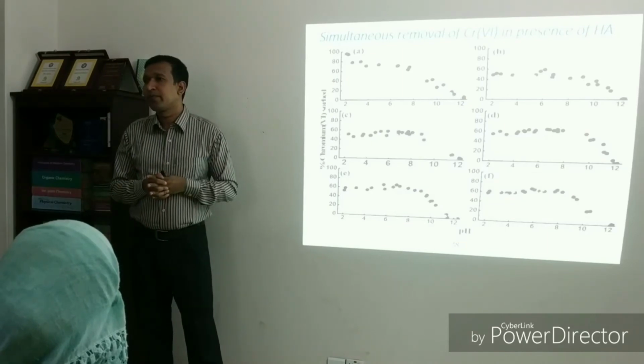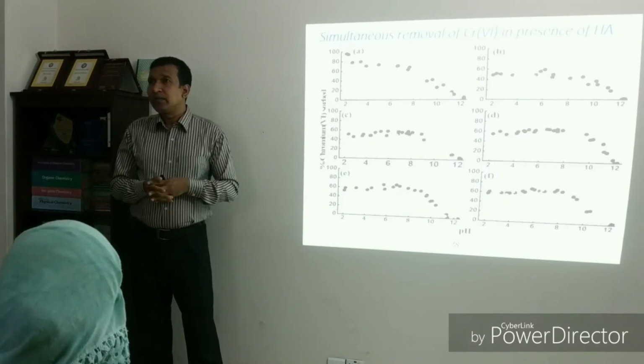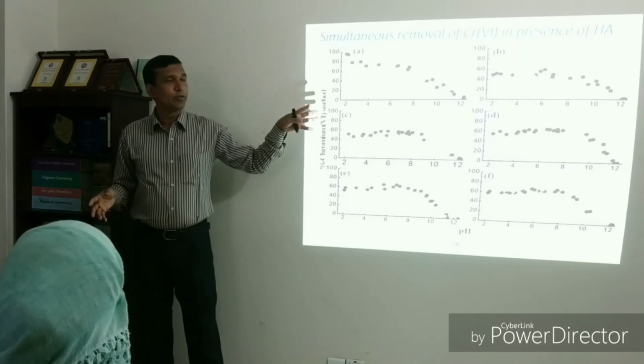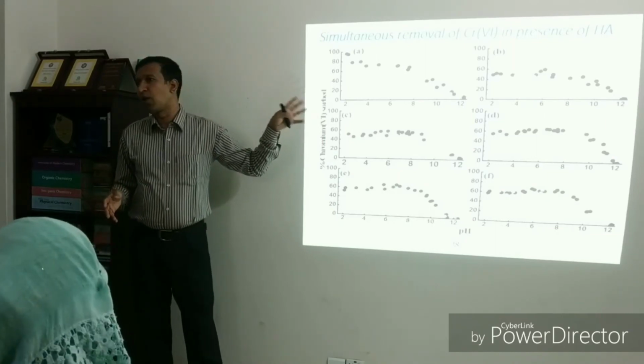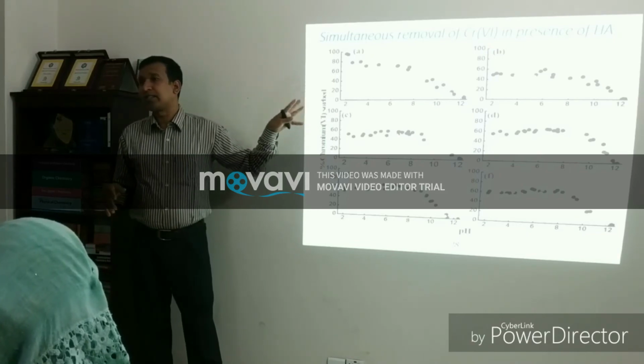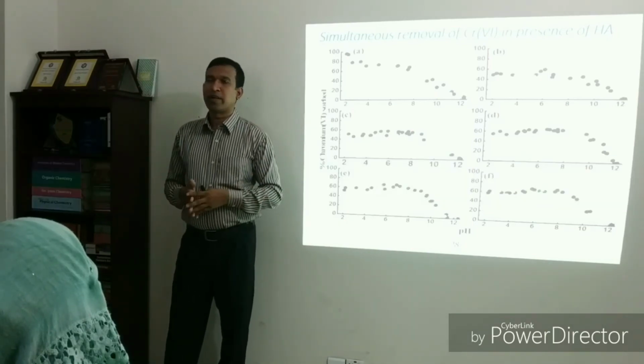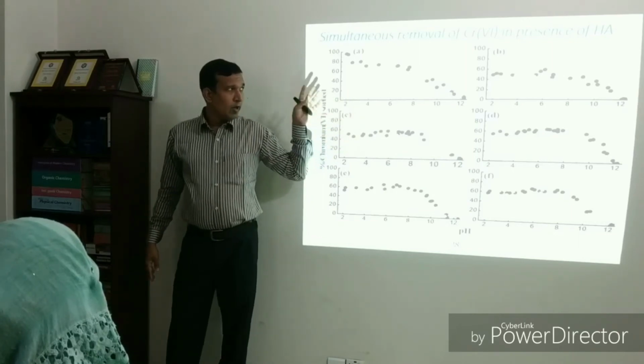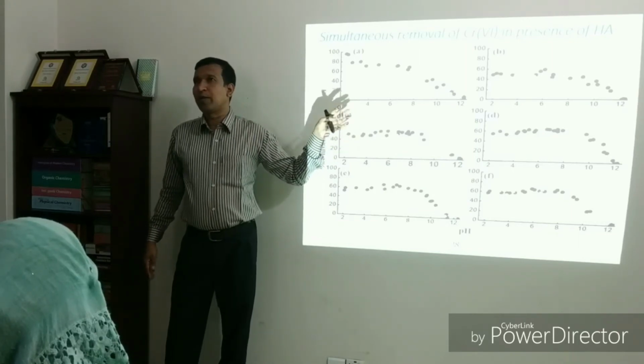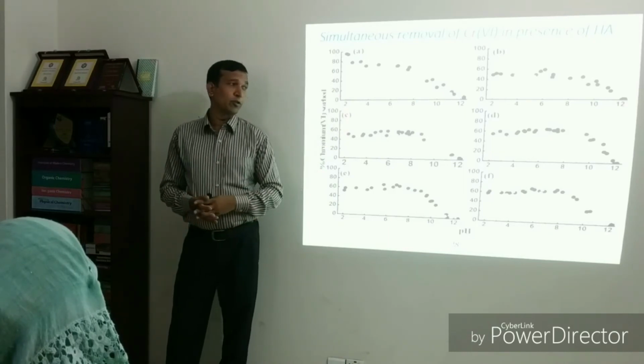Can it be any other molecule except for water? In case of outer sphere complex, can it be any other molecule except for water between surface and pollutant? Usually water, because we use water as the universal solvent. So this system contains only water as a solvent. It could be other, for example ethanol or another solvent, if we use that. But here we have used water solvent in sodium nitrate electrolyte solution. So the possibility is only water.